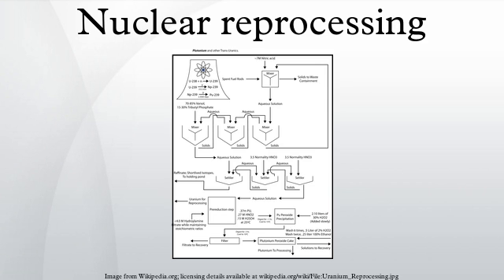Readily applied to high burn-up spent fuel and requires little cooling time, since the operating temperatures are high already. Does not use solvents containing hydrogen and carbon, which are neutron moderators creating risk of criticality accidents, and can absorb the fission product tritium and the activation product carbon-14 in dilute solutions that cannot be separated later. Alternatively, voloxidation can remove 99% of the tritium from used fuel and recover it in the form of a strong solution suitable for use as a supply of tritium.